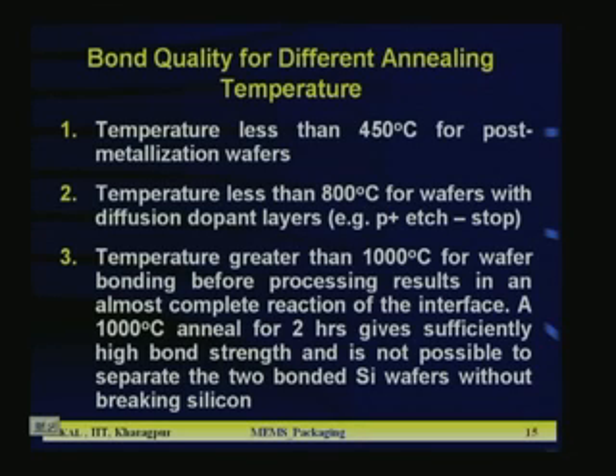Now, temperature less than 800 degrees C for wafers with diffusion dopants, that is P plus etch stop. In some cases you require the P plus etch stop, which will give you an automatic etch stop mechanism. So, there the problem is even if you do not use metal line, if P plus etch stop is there and you raise the temperature above 700 to 800 degrees Celsius, then there is out diffusion and the etch stop layer geometry or dimension will change. As a result you will not get the area of the etch layer same as your design, because the P plus area will broaden externally. So, in that case you cannot go to a temperature higher than 800 degrees C, even if the metal lines are not there.